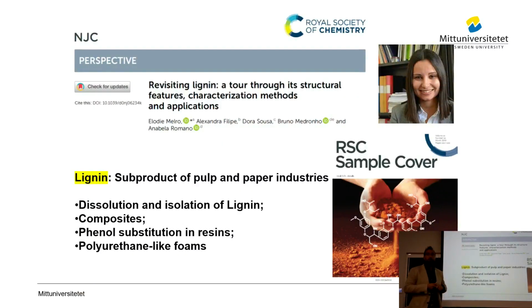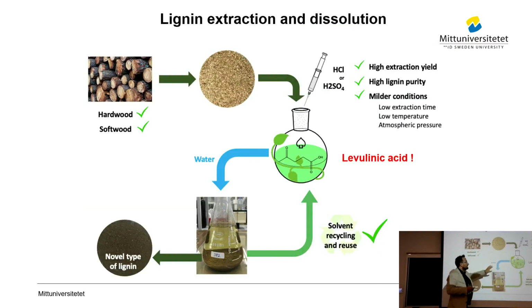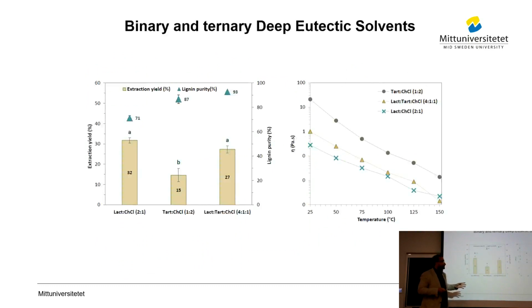Lignin is something that we are working with too. This lady there is about to finish her PhD. She did a lot regarding lignin dissolution and extraction, and a bit also on the development of materials. I just highlight this novel dissolution system based on levulinic acid, where we can really extract high concentrations of lignin with a reasonably high purity, in milder conditions. We can recycle the solvent several times. It works with hardwood and softwood, so we are quite happy about this solvent that Elodie found. And then the lignin properties are different from other lignins, and we are exploring that in other